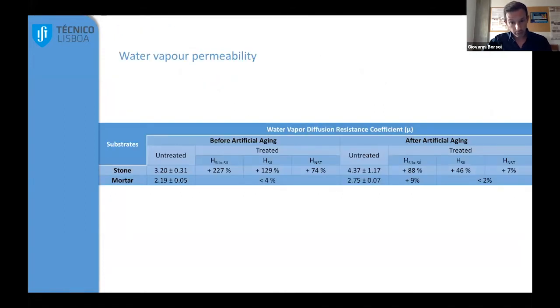Then there is also another interesting part, which is the water vapor permeability. We can see actually that there is a huge increase. So the hydrophobic materials are really affecting the water vapor permeability, and mostly the siloxane-silane products are affecting strongly this behavior. On the other side, the nanostructure is more compatible, or at least less invasive compared to the others. And after artificial aging, once again, the nanostructural materials are much better because there is lower reduction of